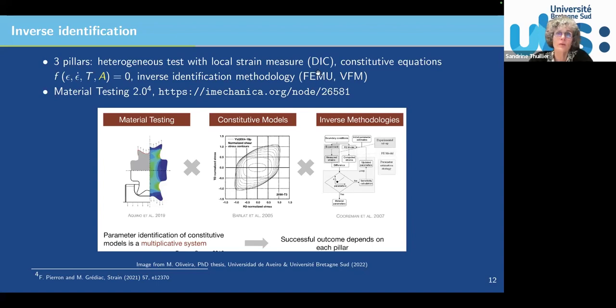In the first one, I would say this is the most straightforward one, you use a finite element model. So let's imagine you've got here on the top the numerical model, the finite element model, and at the bottom, the real experiments. You create a finite element model, you simulate your test, and using an optimizer, you will minimize the difference between the output of the test from the numerical part and from the experiments, and by decreasing the gap in between, you will reach a parameter set.